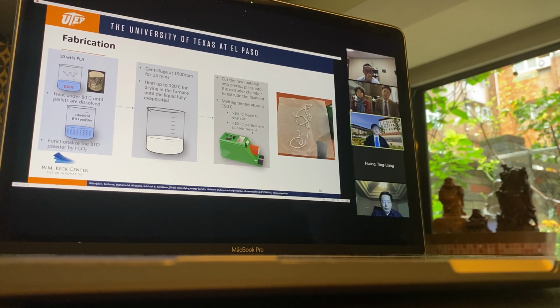So in this step, we test several temperatures to find the best printing point of this composite. In the end, we found 190 degrees Celsius is the perfect temperature. If the temperature is higher than 190 degrees, the material will become too liquid-like and hard to shape. And if the temperature gets lower than this point, the material will be non-uniformly blended.